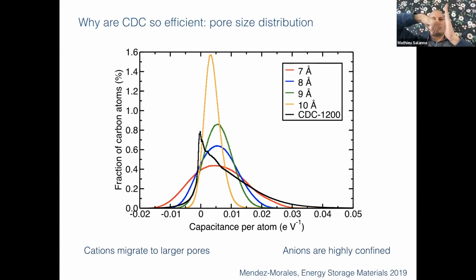And in the 7 angstrom pores, they remain close to the surface, so they will induce a negative charge that is not good. While when you have the complex nanoporous structure, you allow them to go in the middle of the pore, so they are not in close contact with the electrode, and so they are not inducing this large charge on the surface. So in the end, it means that the complex nanoporous carbons, because they have some pore size distribution, allow some good distribution of ions. So the ones that go close to the surface will go, the others go in the middle of the pores. So in the end, you have a synergistic effect between the small pores and the large ones.